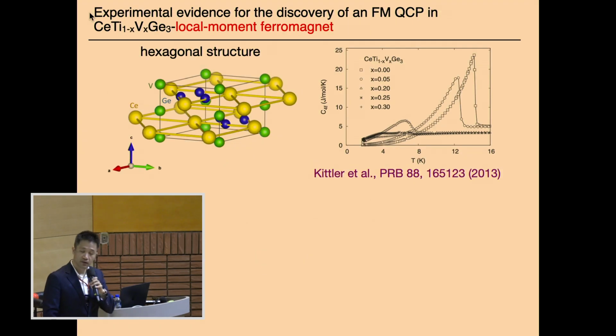So this is the first target compound I work with. The parent compound is cerium titanium germanium 3, which has a hexagonal structure. And it's not new. People have known it for more than 10 years. This is specific heat data versus temperature. And if you look at, so this is 14 Kelvin. At 14 Kelvin, there's a jump. That's cerium titanium germanium 3, which orders